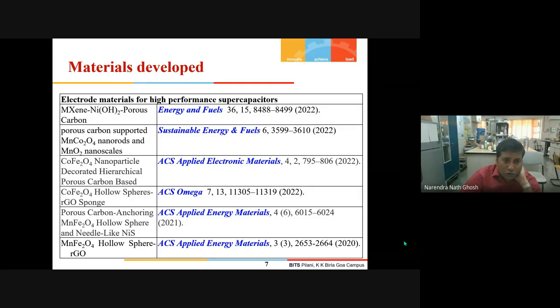We have made the cobalt ferrite nanoparticle decorated porous carbon. These are the nanoparticles, and now we have also made some cobalt ferrite hollow spheres and decorated them on the surface of a sponge-like structure of reduced graphene oxide. I'm sure all of you know what graphene, graphene oxide, and reduced graphene oxide are. Graphene oxide and reduced graphene oxide are thin sheet-like structures, but we have treated it and made a sponge-like structure of RGO.